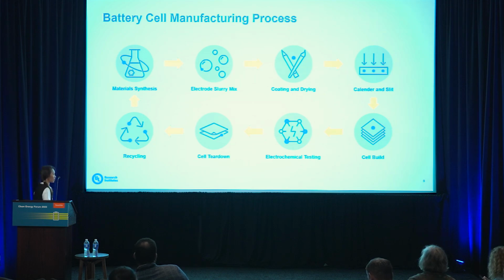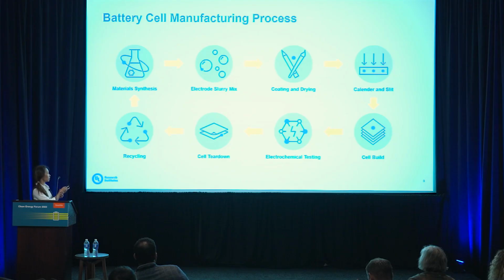So we start with material synthesis. So this is not just mining of materials, but also making sure that the materials become active materials that we can put in our battery slurry. And after that, we do a slurry mix. So this is when we have a recipe for our electrode, and we can put all the active materials in different compositions into a mix.